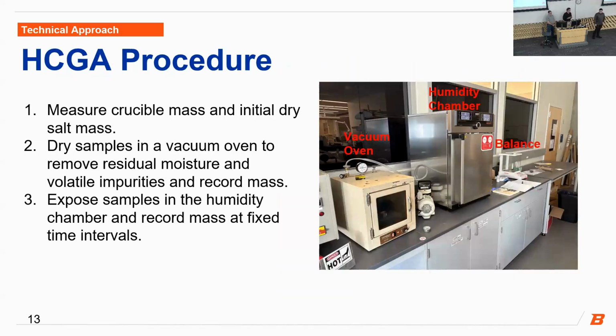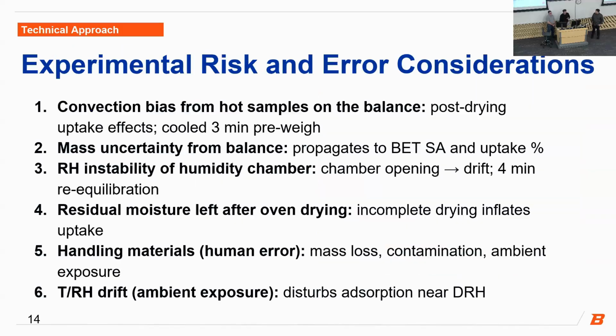Switching over to our humidity-controlled gravimetric analysis, it consists of 3 main steps. The first is to measure the crucible mass and the initial dry salt mass. The second is to dry the samples in the vacuum oven to remove that residual moisture and any impurities, and then record the mass once again. And then the third is to expose the samples in the humidity chamber and record the mass at fixed time intervals.